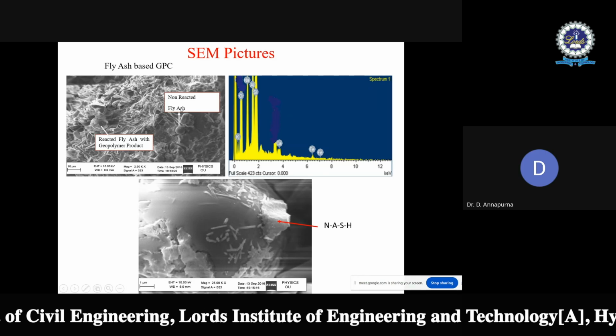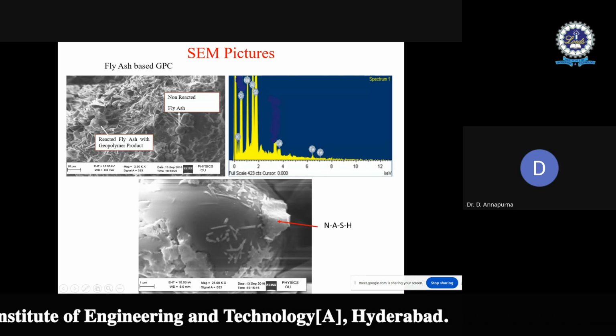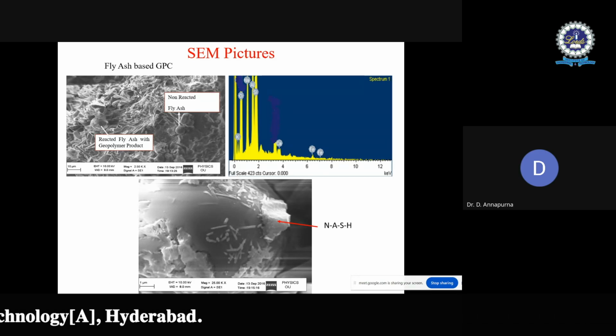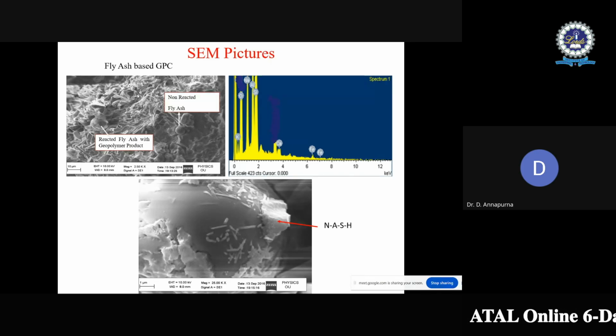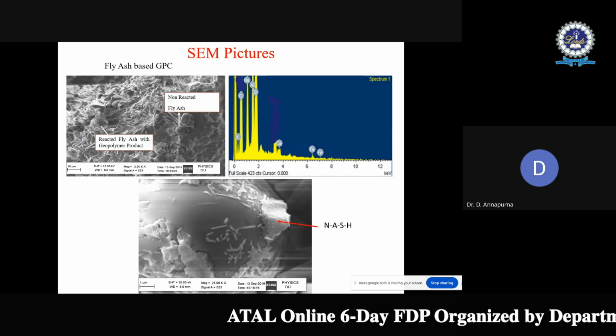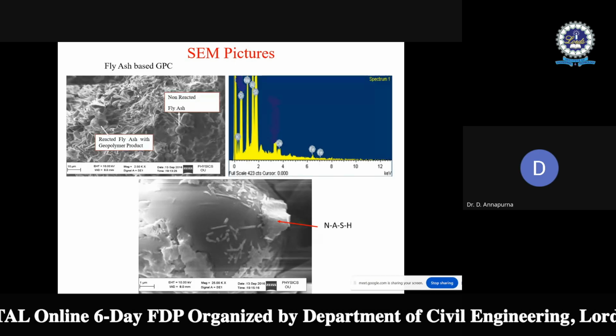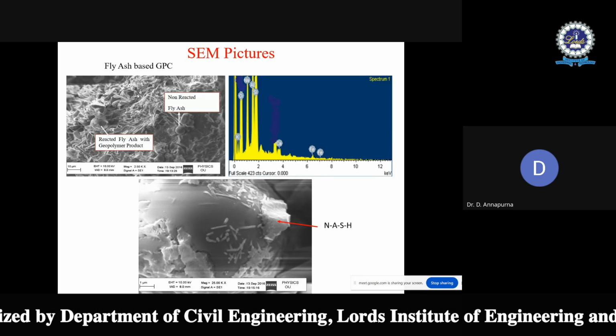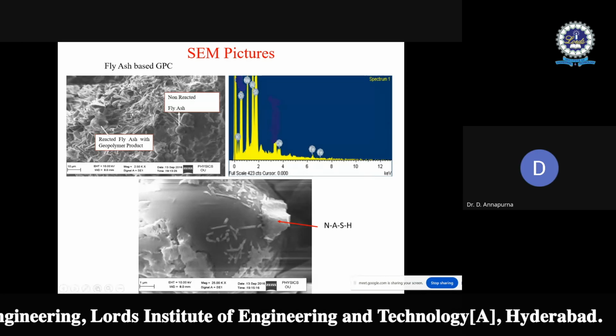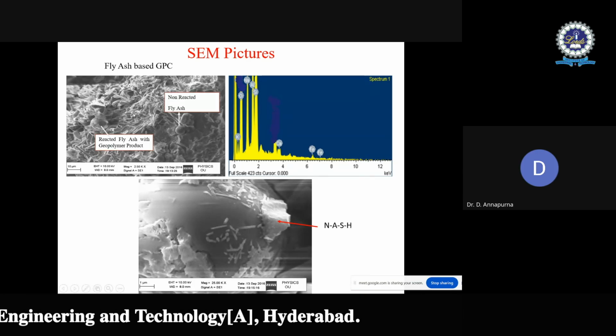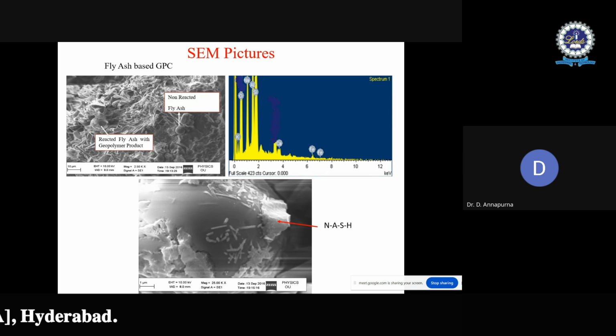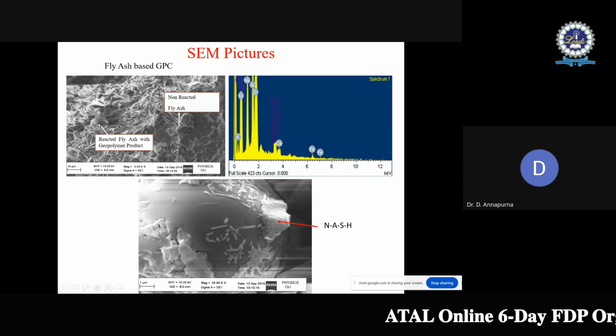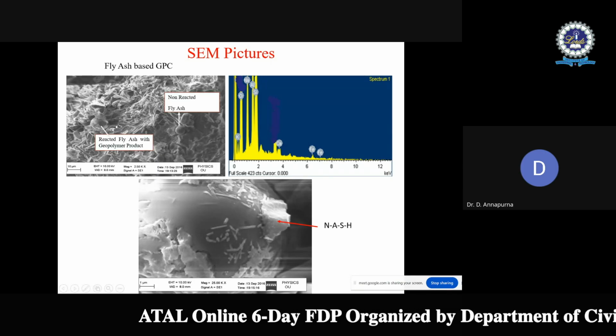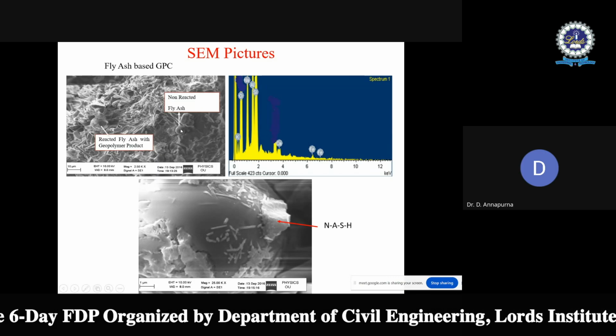First one is fly ash based geopolymer concrete. To see how the geopolymerization process varies in terms of microscopic observation, first we tried with fly ash based geopolymer concrete. That means only fly ash is used in the production of geopolymer concrete. In that, a 28 days cured sample is taken. So in this, this is reacted fly ash, this cenospherical shape is depicting the fly ash. On top of that, geopolymer product is there, and these are non-reacted fly ash.